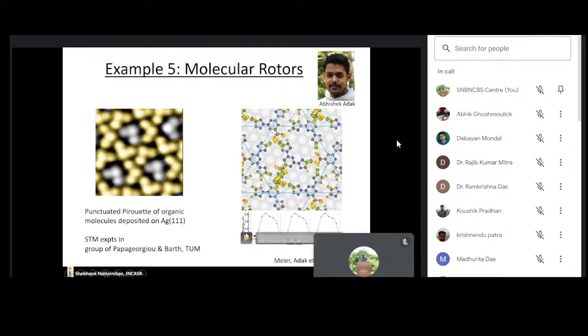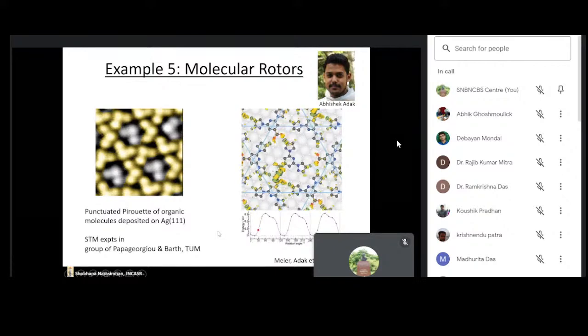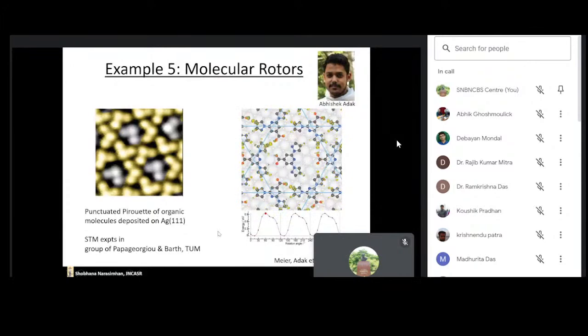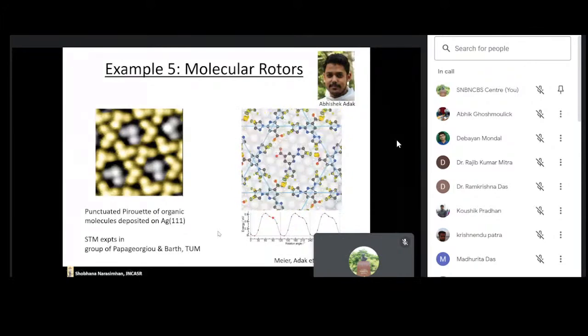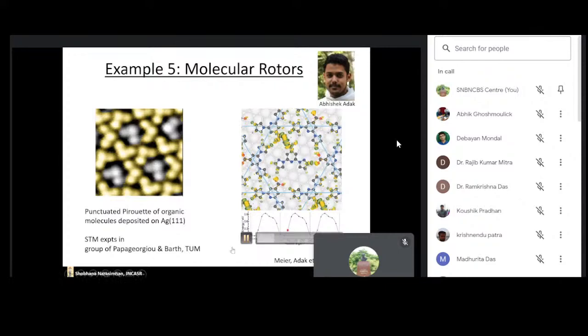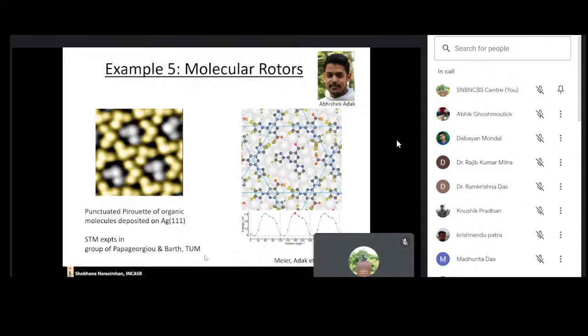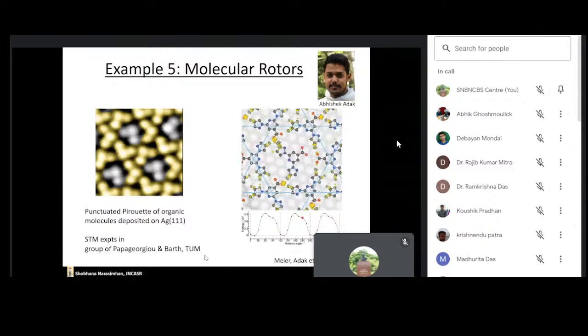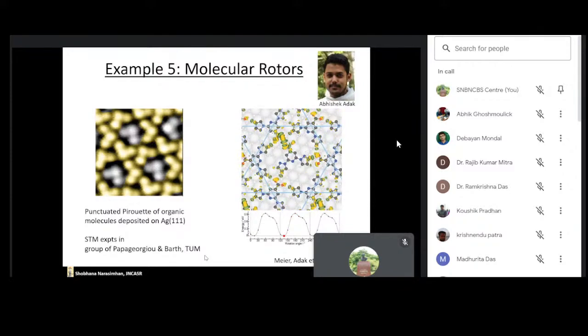So now I will play this video, and you will see in our theoretical calculation, we can see the molecule rotating, and as it rotates, you can see that bonds are formed and broken, and accordingly, the energy changes according to this graph shown at the bottom here. So the red dot shows where on this energy landscape you are as you rotate, and you can understand why you have high energy at some places and low energy at some places. You have low energy where the structure is stabilized by the formation of lots of hydrogen bonds, and you have high energy where you have very few hydrogen bonds. And so we can study this whole energy landscape, and you can understand the dynamics of the rotation.